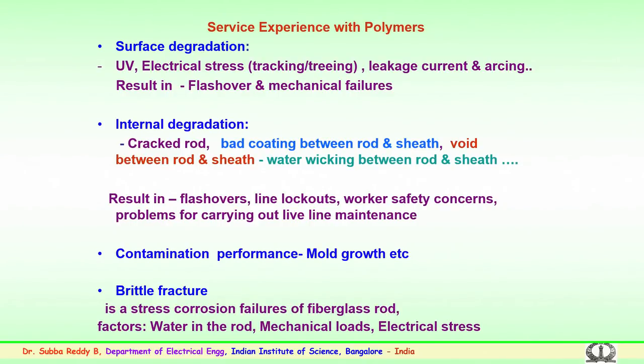Some reports have indicated mechanical failures because of degradation. Similarly, internal degradation could happen because of a cracked rod, as I mentioned, in the manufacturing stage or during stringing, when there could be internal damage. Because of the end fittings' pressure, micro cracks could have happened and could develop over a period of time, or this could be because of the coating between the rod and sheath before the silicone rubber material is molded on the fiberglass rod.